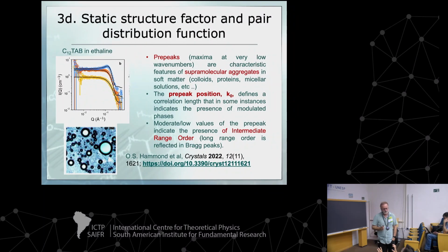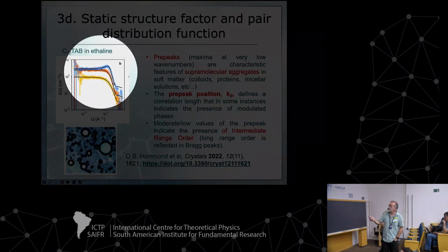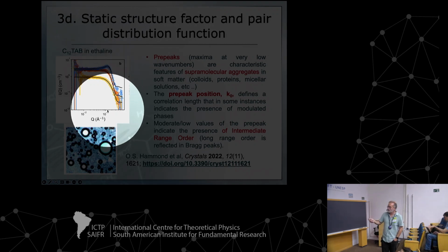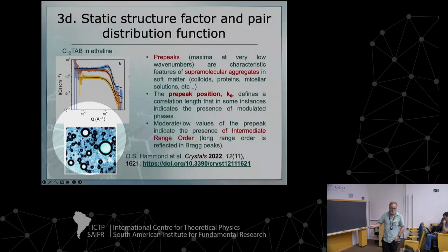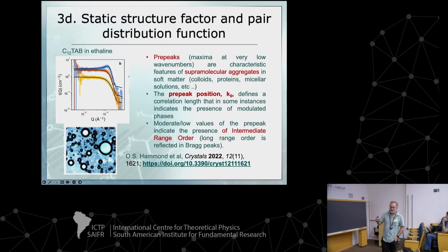Usually when you have surfactants, they are polydisperse. Polydispersity is the reason for the peak being more wide. That's the reason, because the peak doesn't look that wide here, but it is, because this is a log scale. So the peak actually goes over not an order of magnitude, but almost. And you see here that this is very, very, very polydisperse. That's the case of surfactants.